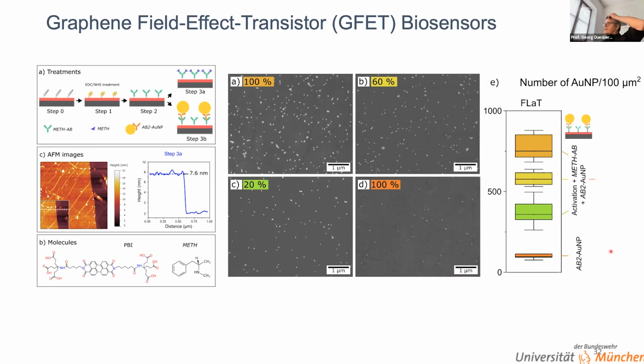And we made some statistics over this work. I have to admit that you get a lot of clusters also on the normal functionalized surfaces. However, they're much less homogeneous. So we actually believe that those things like to attach to, let's say, the polymeric residues quite a bit. So it's not so much about the absolute number, it's about the homogeneous distribution of those clusters, because they act as binding sites for the analyte, which is in this case methamphetamine, or in colloquial language speed, a drug, which is very interesting because it's a small molecule, which always had been thought to be very hard to detect.